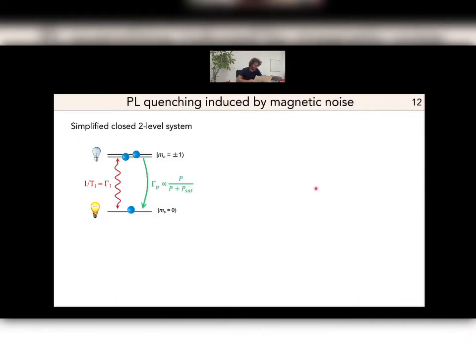For that, I would like to show you that there is also a quenching of the photoluminescence of the NV defect that is induced by magnetic noise. So for that, we again rely on a simplified two-level system where we have the bright state and the dark state, and we have the competition between two effects. The green arrow here shows the optically induced spin polarization in ms equals 0. Essentially, this is the optical illumination that brings the population into ms equals 0.